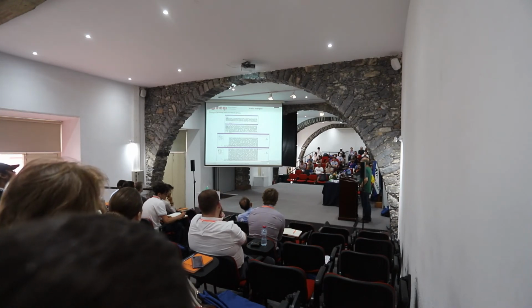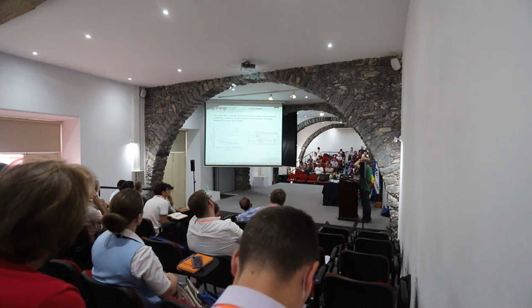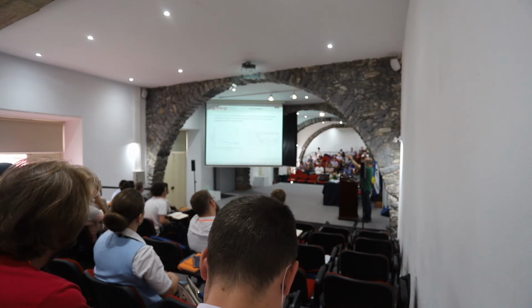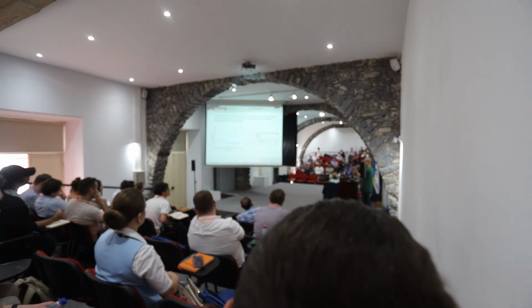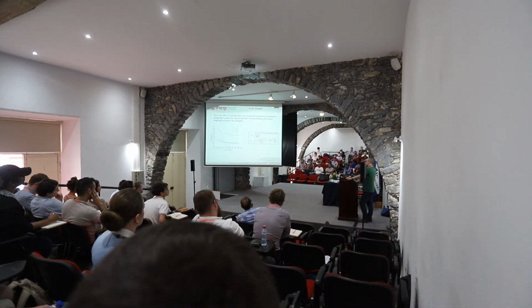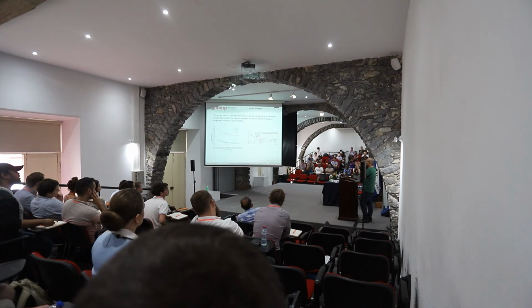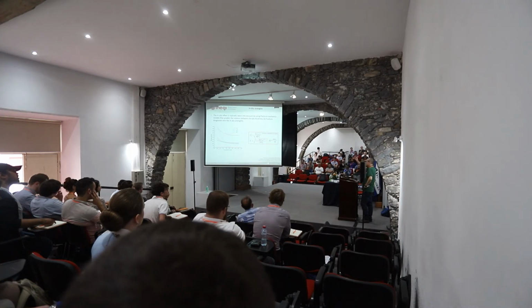Now, what I would like to show you is the use of computational micromechanics. This work was done in collaboration with NASA Langley right after an accident at Lockheed Martin, because NASA realized that they didn't have the right models to simulate delamination. That's why we worked a lot on cohesive zone models in the early 2000s, and then we realized that the end result was a delamination, but the root cause was a transverse crack. So then we had to work on failure criteria, and that's why we started looking, in 2005 or thereabouts, at size effects and in situ strengths.